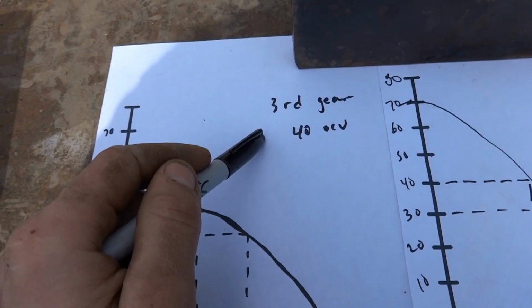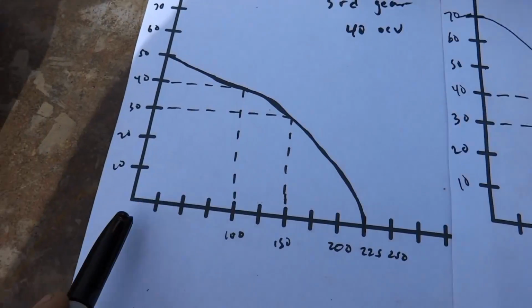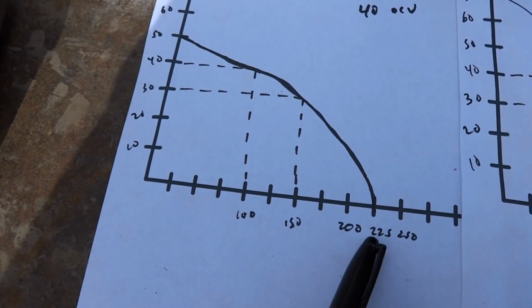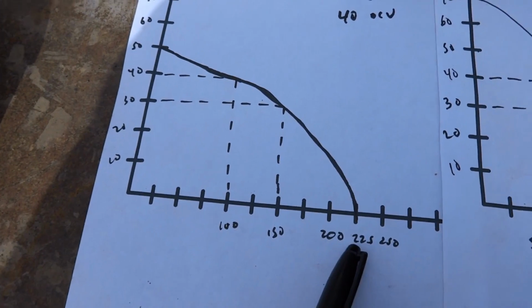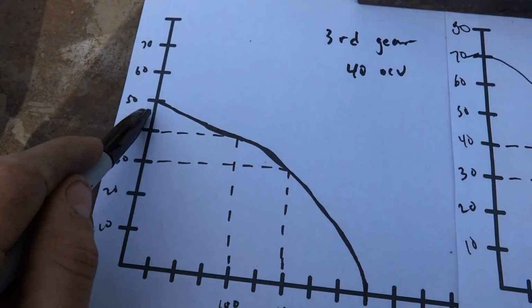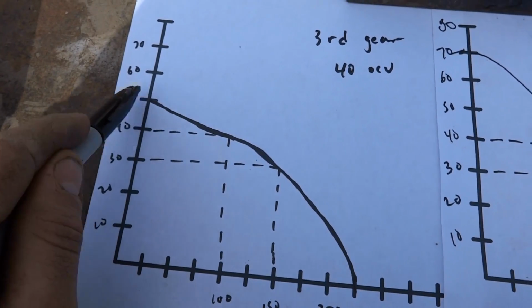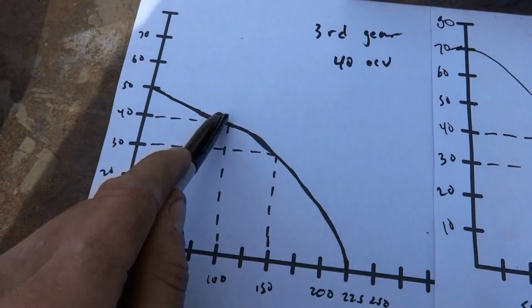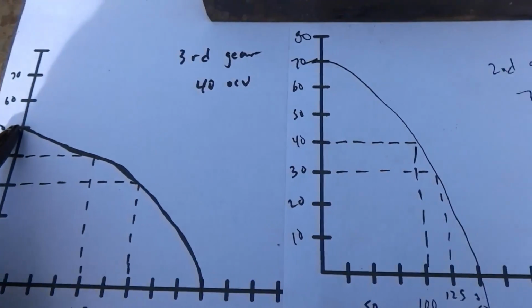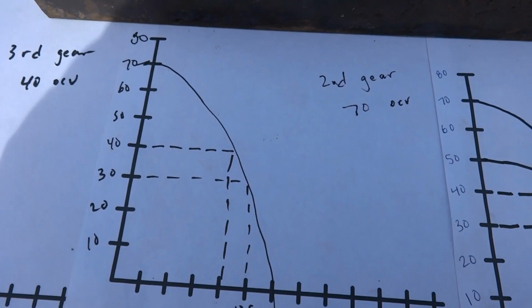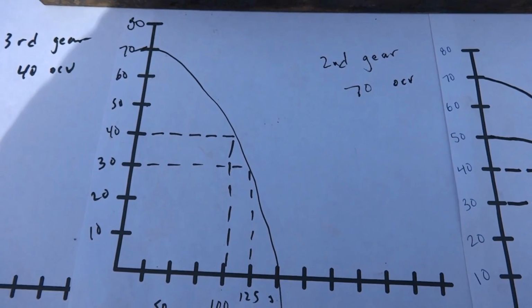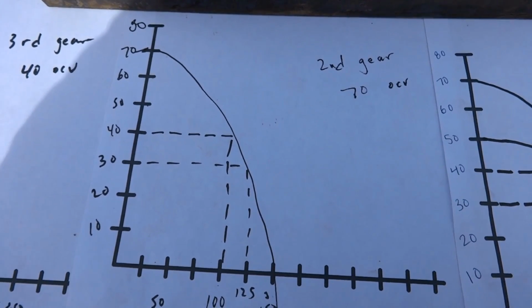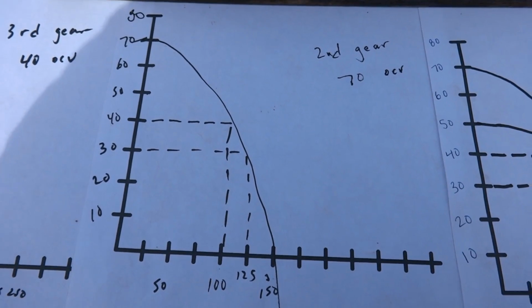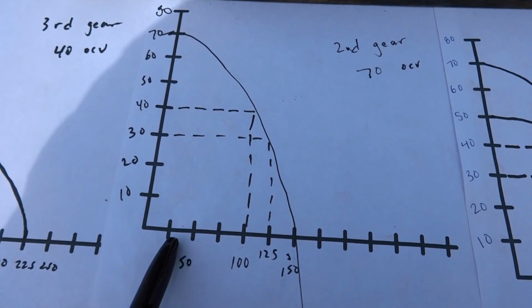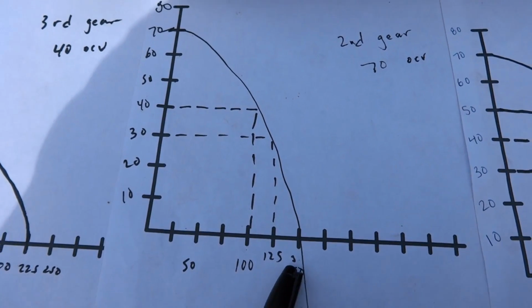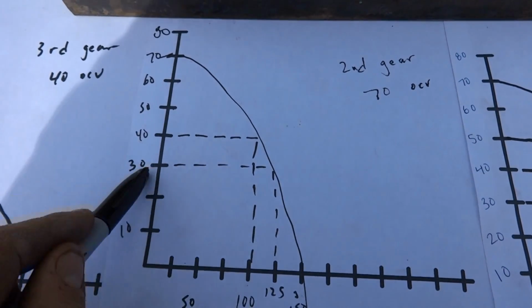Now we're at high amperage, low voltage. We're at high amperage, 225 amps. We're at low voltage. Voltage is 50. This is a volt-amp curve. Over here, this is 2nd gear, 70 volts. We're at a low amperage range and a high voltage. In the low amperage range, we only go up to 150 amps. Well, we have a lot of voltage. The voltage is all the way up to 70.